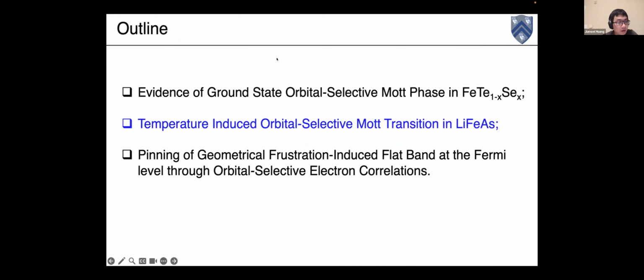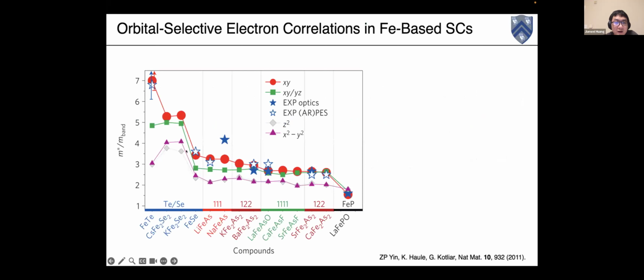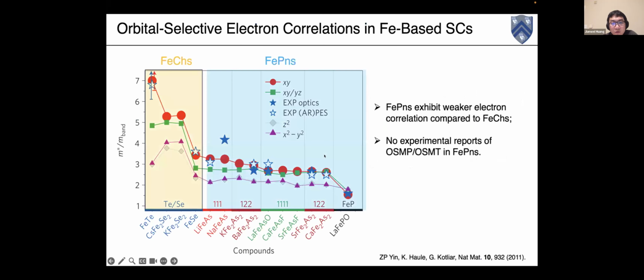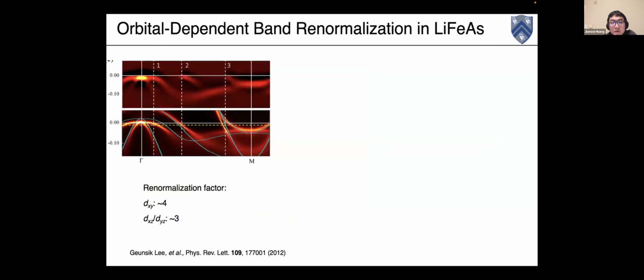So the second part is I will talk about the temperature-induced orbital-selective Mott transition in the iron pnictide, in iron arsenic. So we know that the iron chalcogenides usually possess a stronger electron correlation than iron pnictides. So although there's been a universal temperature-induced OSMT or even ground state OSMP phase observed in the iron chalcogenides, as far as I know, there are no experimental reports of this OSMP phase in the iron pnictides. And if we were to find the OSMP phase in the iron pnictides, we want to really look into the crystal that has the strongest correlation among them, for which lithium iron arsenic, LiFeAs 111, could be a very good case.